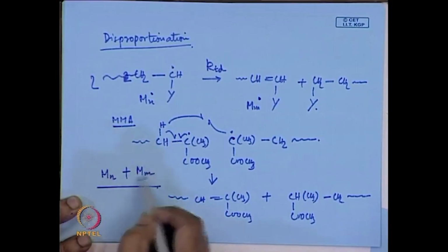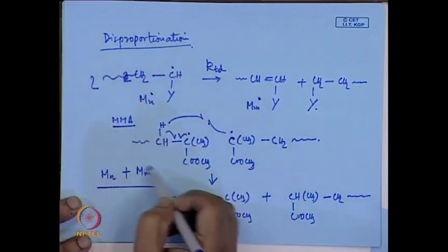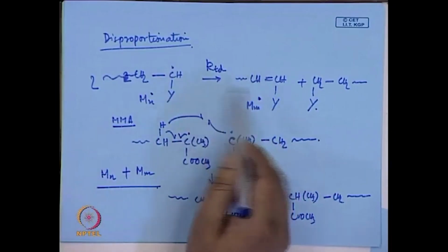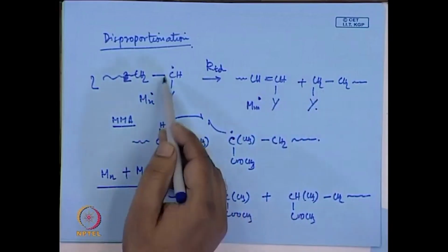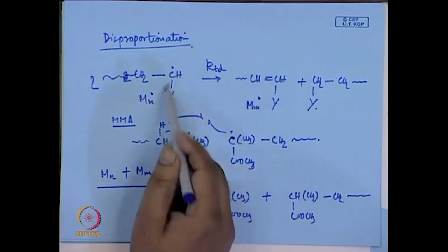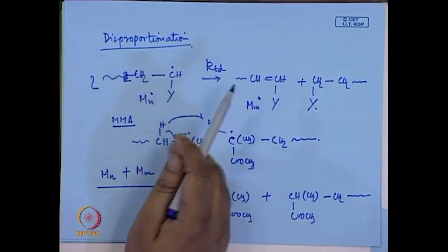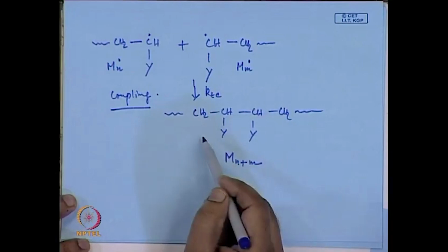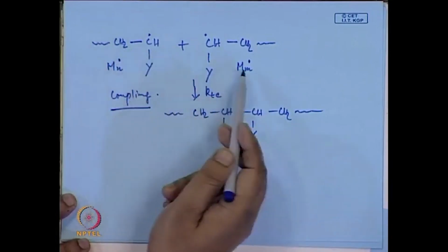Here the molecular weight does not change on termination, ignoring the difference of 2 hydrogens, so the dead polymers have the same size as the reacting polymers. In the earlier case, the length of the final terminated chain is the sum of the sizes of the two reacting species.